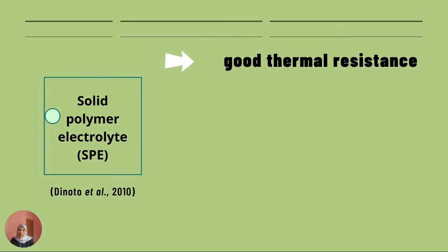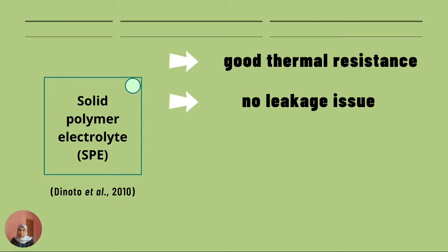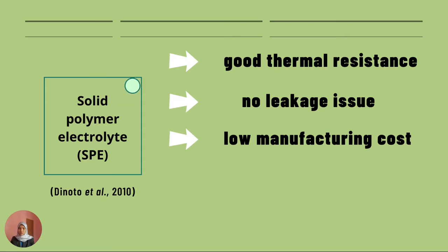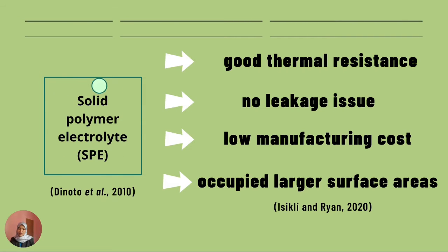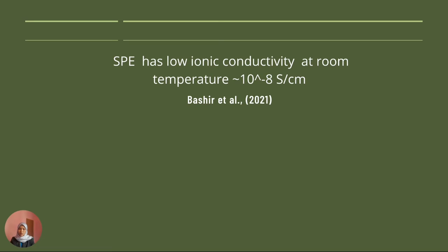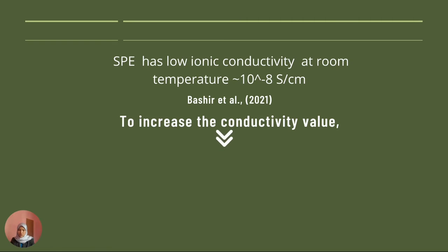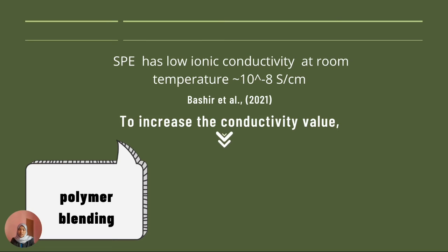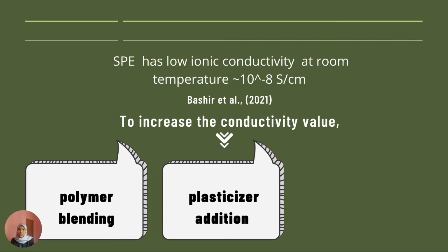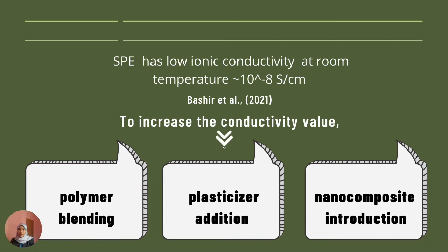This is because it has good thermal resistance, no leakage issues, low manufacturing costs, and occupies larger surface areas. However, solid polymer electrolyte exhibits low ionic conductivity at room temperature, approximately 10 to the power of -8. Hence, in order to increase the conductivity value, there are three main alternatives that have been introduced, which is polymer blending, plasticizer addition, and the introduction of nanoparticles.